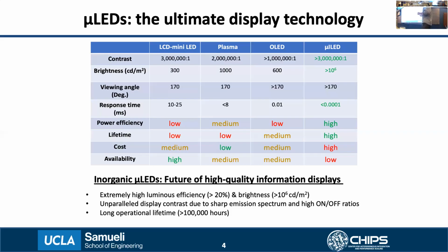Yeah. In the case of things like LCDs, you essentially have the liquid crystal layer, which controls the polarization of the light. Those have a much larger inertia when they are electrically activated compared to something like micro-LEDs. And OLEDs, because they are an organic material, also have electron mobilities that are much worse compared to micro-LEDs. Materials such as gallium nitride and indium phosphide are known to have very high electron mobilities because of their band structures. That's why they have several orders of magnitude better response times compared to those other display technologies.